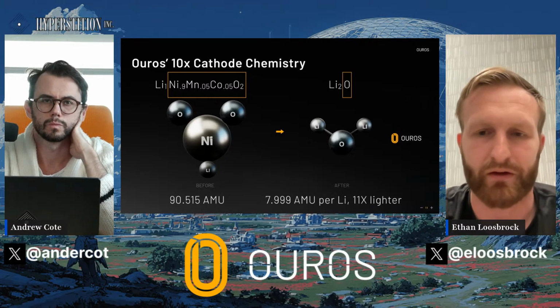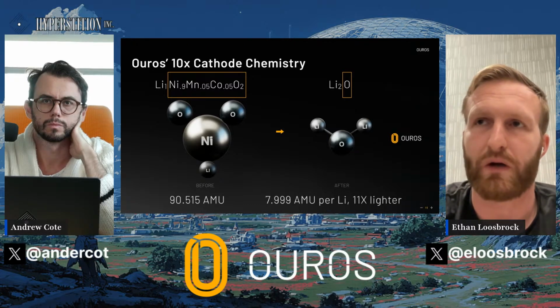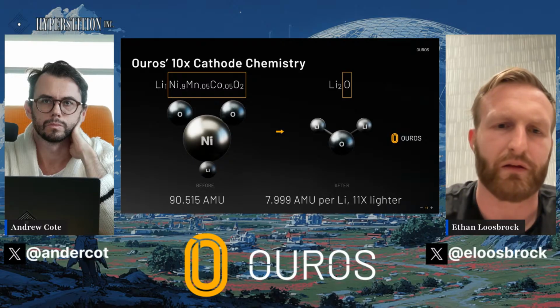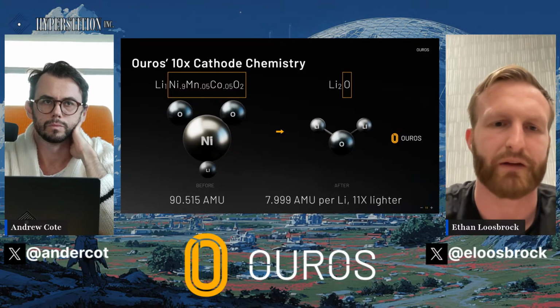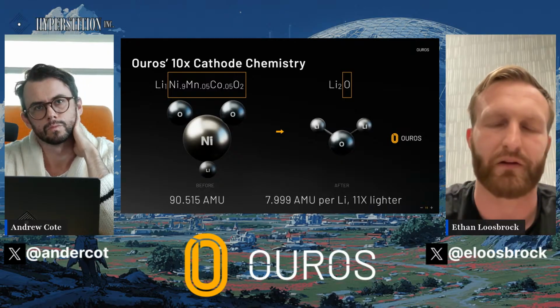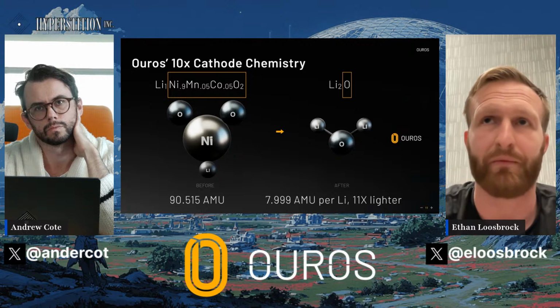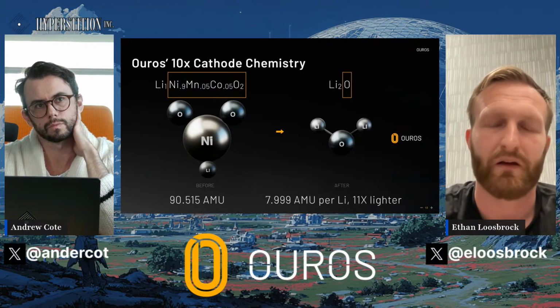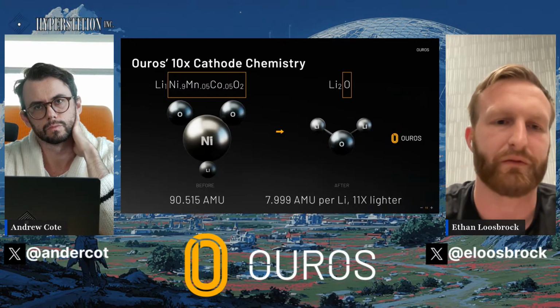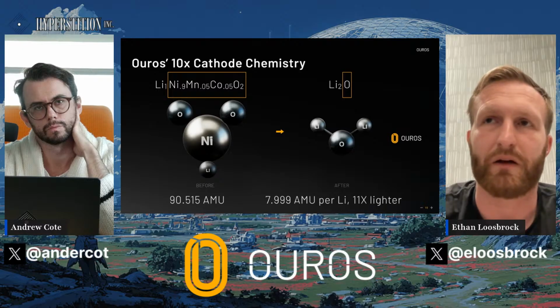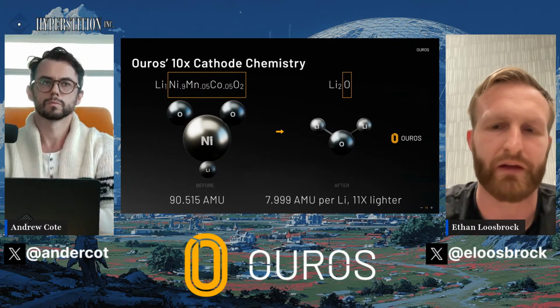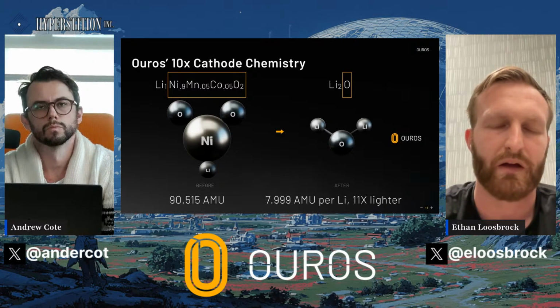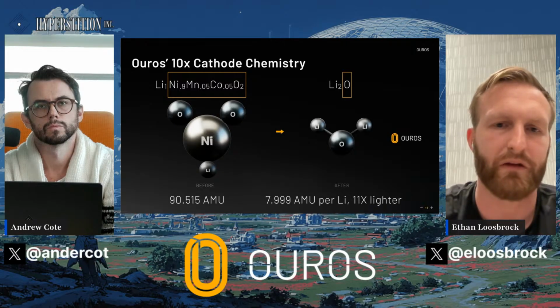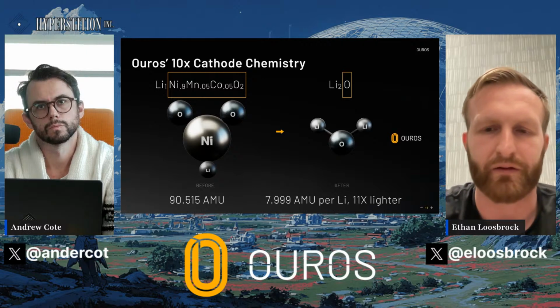The other challenge, like you said, is that there are still side reactions. Like with any new battery chemistry, you tend to start at zero, but the nice part about this chemistry is it's still lithium, it's still a metal oxide, so you can tap into a lot of the work that's been done thus far on additives and electrolytes. We've been able to shortcut, I'd say, 75% of that development, but Coulombic efficiency is still definitely a challenge. And the other part of it is lithium oxide is relatively insulating compared to lithium nickel oxides, because that nickel confers electrical conductivity. And so oxygen doesn't quite do that as well.